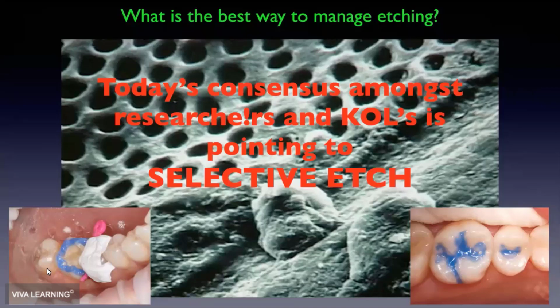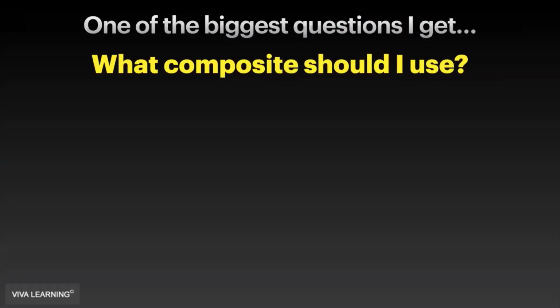The little picture on the lower left actually shows preparation for bonding in an onlay. This onlay has enamel around the edges as the margins, and of course a big lump of dentin in the middle. So this is what we mean by selective etching: I would lay down phosphoric acid on the enamel for 20 to 25 seconds, wash it away, and then apply my self-etching primer and adhesive, whether it's a 6th generation, which is two-step, or a universal, which is a one-component material, scrub that in for the prescribed amount of time, and I'm ready to go.